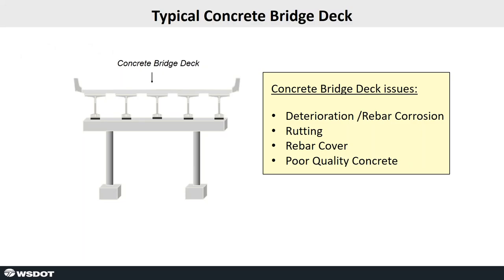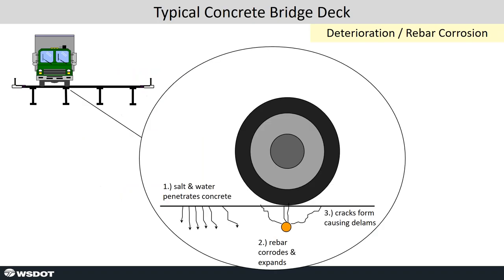So what are the issues that we're looking at on the preservation side? We're looking at deterioration, rebar corrosion. That's the primary one. Anthony talked a little bit about rutting because of our studded tires. Sometimes in the past, if a bridge deck was not correctly built, the rebar would be exposed easily, and that becomes a problem over time. And then sometimes the quality of the concrete was just poor from the very beginning.